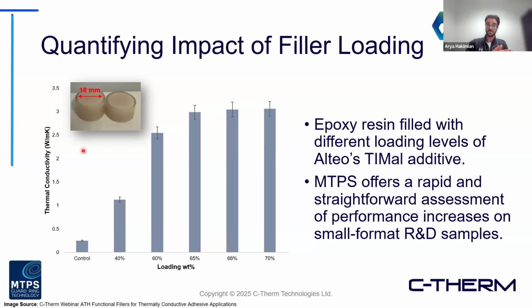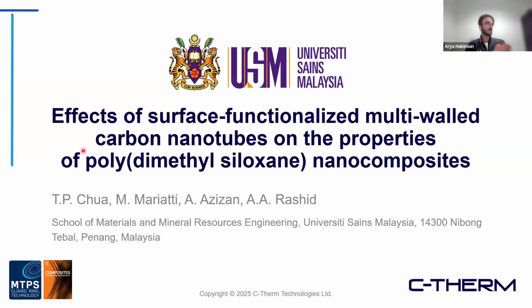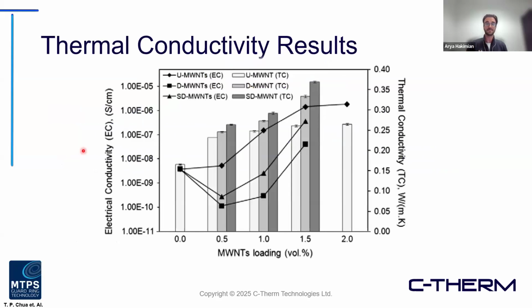Now, of course, we're introducing fillers and seeing that net increase, but you can also look at some other factors here. This is a publication from a couple of years ago looking at the impact of different functionalized multi-wall carbon nanotubes on the nanocomposite properties. This was some interesting research coming out of Malaysia, again using the MTPS, but while they were still looking at different loading levels of this filler, on top of that they're varying the specific type of filler. So at the same loading level, we're seeing different behavior, different net increases to thermal conductivity, based on the functionalization that was used on that filler.